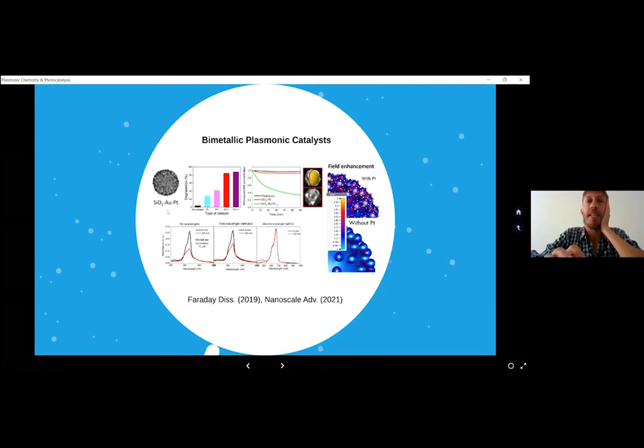So here we're combining the ability of gold to harvest light and excite plasmons, and the ability of platinum to catalyze chemical reactions quite efficiently. So Jorge tested many different things, from the amount of platinum that you can load to the size of the plasmonic nanoparticles, and they tested this towards the degradation of some organic dyes.